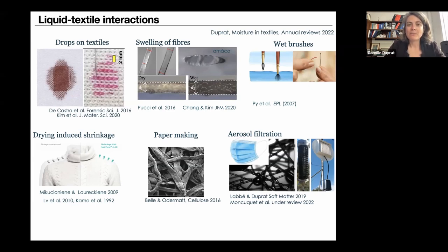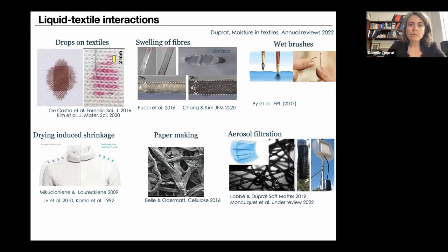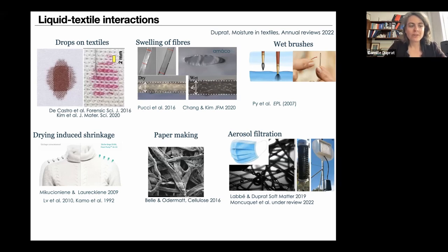The yarn is made of individual filaments, and as liquid spreads it will spread between the filaments, between the yarns, and inside the fibers themselves. For example, a drop of blood splattered on a textile imbibes faster in the warp direction than the weft direction because of the tension within the weave that changes the shape of the yarn. The liquid can also get inside the fibers because most fibers — cotton, cellulose in paper, filters, face masks — absorb water and swell.